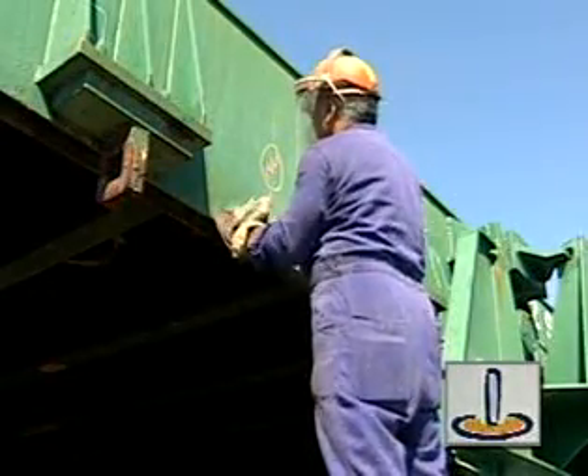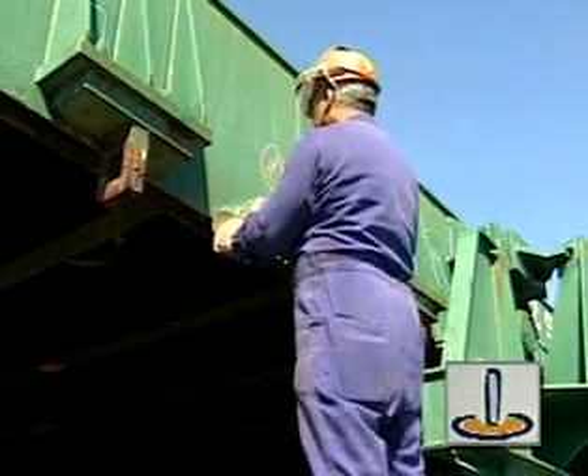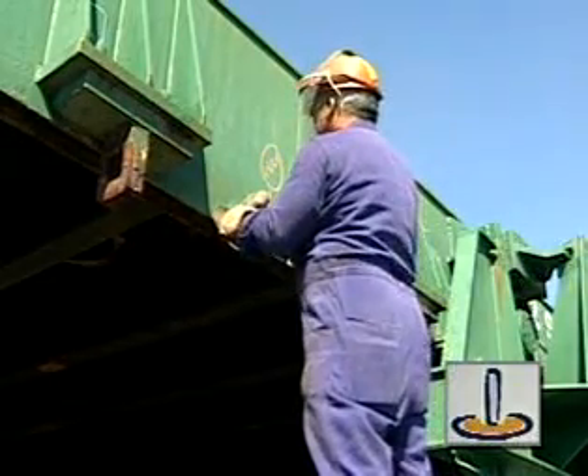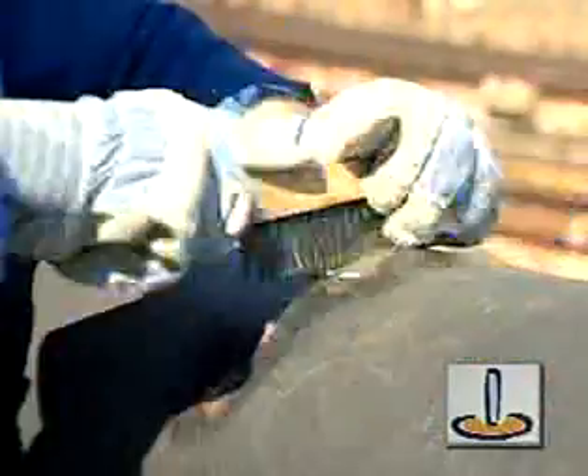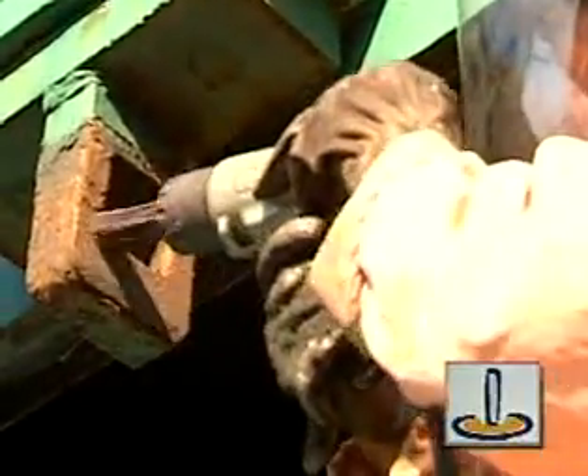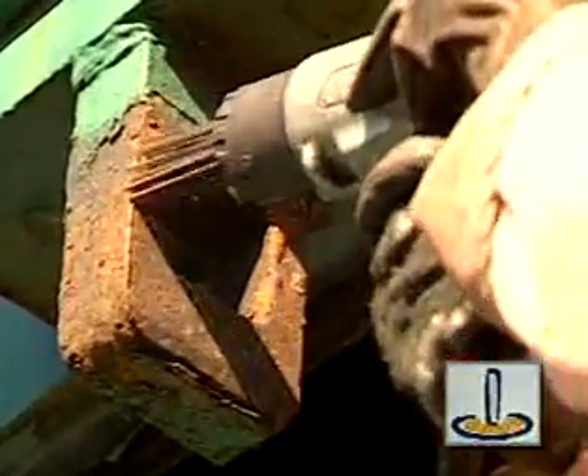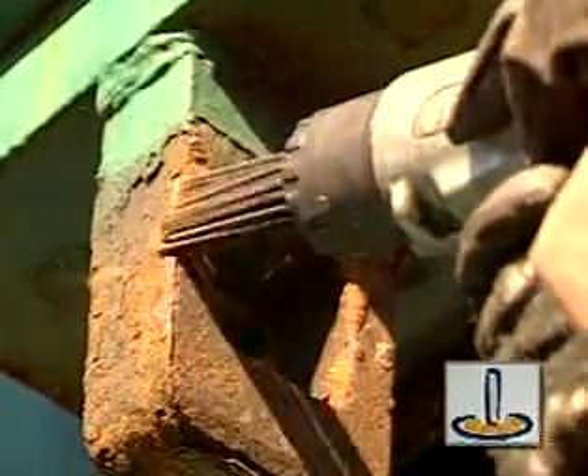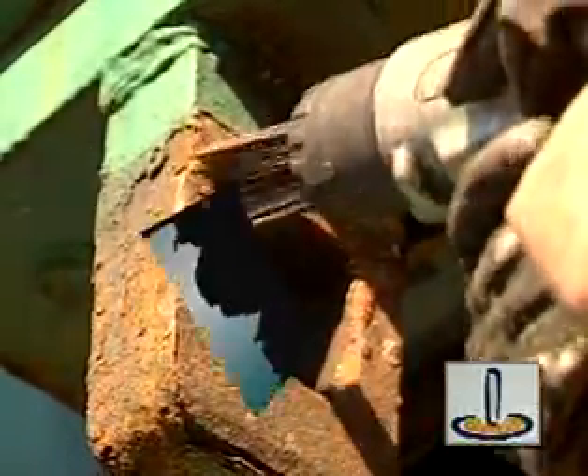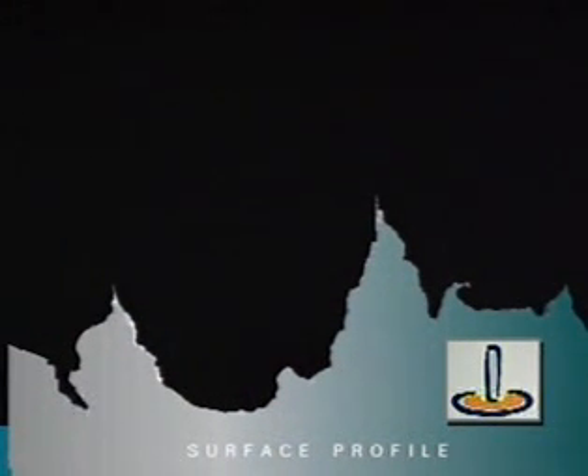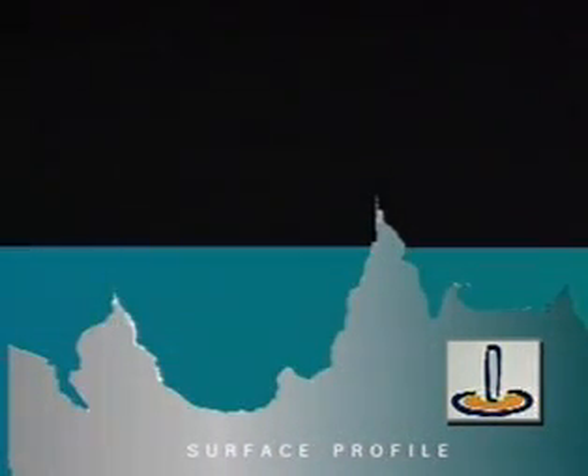Generally, use light strokes to prevent the power tool biting into the steel surface, causing it to be too rough. For small areas, wire brushing or power wire brushing can be used to remove all loose corrosion. For difficult corners, uneven surfaces and angled areas, a needle gun may be used. Hold it firmly, but do not allow the gun to dig into the metal surface. Otherwise, tiny points of steel will form and subsequently stick up through the coating, causing fresh corrosion to occur.